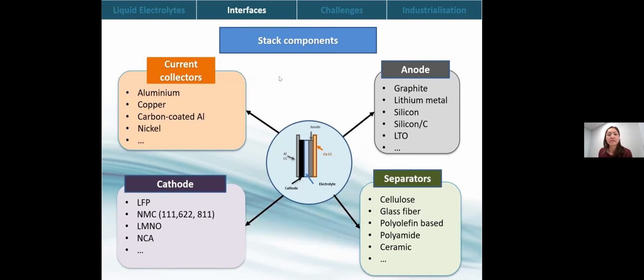When we talk about electrolytes and interfaces, it's very important to look through the whole stack of components, especially when the electrolyte is liquid. We have to look at interactions with the current collectors. Different electrolytes will react differently with different current collectors, like aluminum, copper, or carbon-coated aluminum. Even if it's stable with aluminum, when there's a carbon coating, carbon can have a lot of functional groups depending on the activation processes, and this can result in early decomposition of the electrolytes. Then you also have reactions with nickel and so on. On the anode side, we also have to test the stability with graphite. The same electrolyte that works with graphite might not work well with lithium metal, pure silicon, silicon-graphite, LTO, and so on.